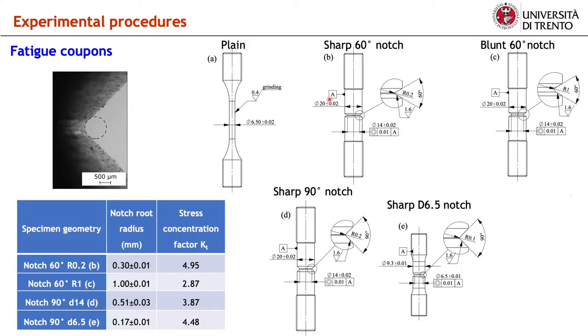The fatigue characterization was conducted using axisymmetric specimen geometries. Specifically, the plain specimen geometry was used to determine the material's baseline fatigue S-N curve. V-notch specimen geometries are characterized by a notch tip, which was optimized to maximize the intensity of the asymptotic stress field. Specimens B and C have a notch opening angle of 60 degrees and differ only in the notch tip radius, whose nominal value was set equal to 0.2 and 1 millimeter respectively. In the following, they will be denoted as sharp and blunt notches.